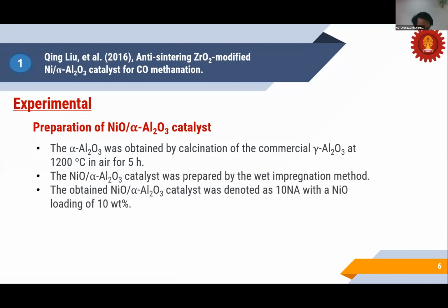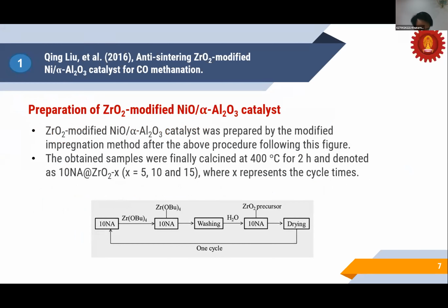Secondly, the literature review. The first paper is anti-sintering zirconium oxide modified nickel catalyst supported on alpha alumina for CO methanation, published in 2016. Experimental: the obtained nickel oxide on alpha alumina catalyst was denoted as 10Na with a nickel oxide loading of 10 weight%. Zirconium oxide modified nickel oxide on alpha alumina catalyst was prepared by the modified impregnation method. After the above procedure following this figure, the obtained samples were denoted as 10Na zirconium oxide-X, where X represents the 5, 10, and 15 cycle time.